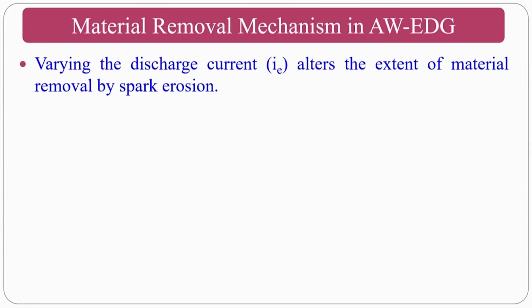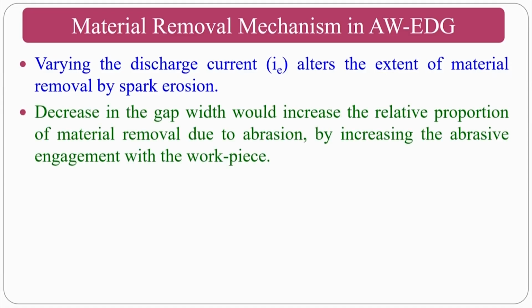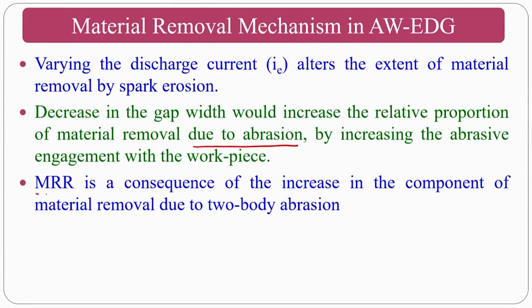Varying the discharge current alters the extent of material removal. As I said, if you increase the current, the melting will take place and thermal softening of the workpiece takes place. A decrease in the gap width would increase the relative portion of material removal due to abrasion. If you have very little gap, what will happen? If you have seen the previous mechanism of the thermal softening clearly, the abrasive particle is protruded out. So normally the abrasion action will take place more. That means the dominating abrasion action will take place. MRR, that means the material removal rate, is the consequence of increasing the component of material removal due to two body abrasion. That means that if your current is very less, normally the material removal is the consequence of the increase of the component of two body abrasion.